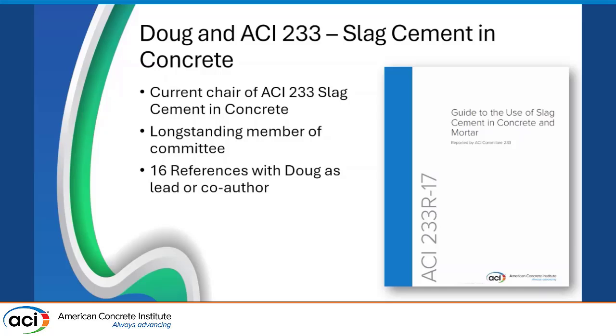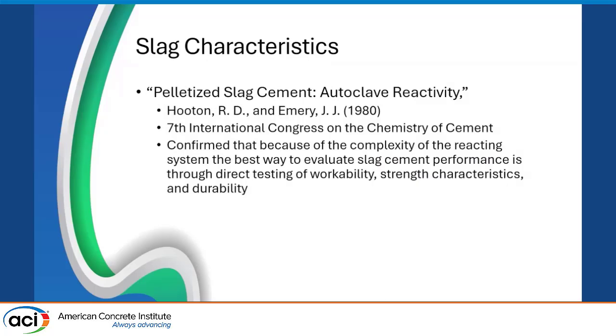I looked at that, and there are 16 references in our current report for ACI 233. Since those were the ones cited, I thought I'd take a quick look at each and see the different areas that Doug had a hand in, and there are many. For instance, on slag characteristics, there was a paper called Pelletized Slag Cement Autoclave Reactivity. It confirmed that because of the complexity of the reacting system, the best way to evaluate slag cement is not necessarily by looking at the materials it's composed of, but through direct testing of workability, strength characteristics, and durability.